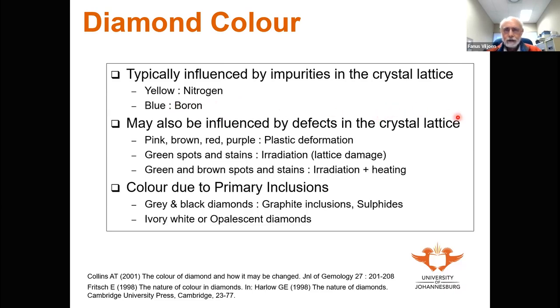Diamond color may also be influenced by defects in the crystal lattice. And so, for example, diamonds reside in the mantle at high pressures and high temperatures, where they can be easily deformed. And so if there is, for example, cratonic deformation through, for instance, mountain building processes, or for that matter, sampling of the mantle by the kimberlite may also deform the surrounding mantle, you would end up with essentially pink, brown, red, or purple diamonds due to the plastic deformation.